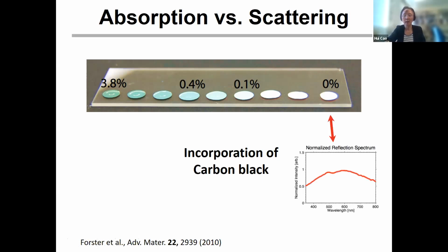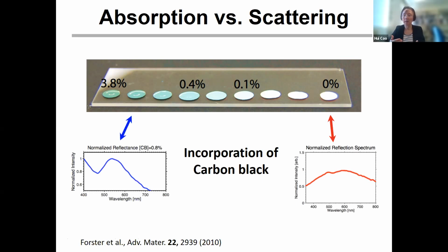What happens here is that initially, as I said, all the colors can be reflected because the sample is thick. But later on, because there's carbon, it is going to absorb light. The blue light will be quickly reflected because its reflection is enhanced. So that's why it can still come out. But the red color has to go a longer distance before it can be reflected, and before it's reflected, it has been absorbed. So that's why we can see this kind of reflection peak in this optical spectrum here. That means if we mix black and white, carbon black with this paint, what do we get? We don't get gray, we get color, like this green-blue color. That's coming from this interplay between absorption and light scattering.